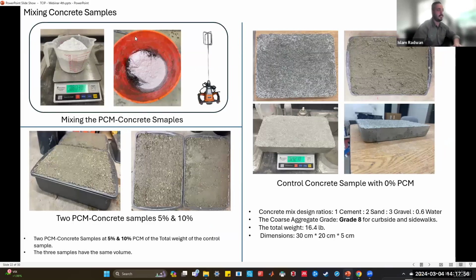Those are real pictures of the mixing. On the right-hand side, we can see the control concrete sample with 0% phase change material. We use the ratios 1 cement, 2 sand, and 3 gravel, and 0.6 water ratio. And also the coarse aggregate was grade 8. And on the left-hand side, we can see the mixing process of the PCM.